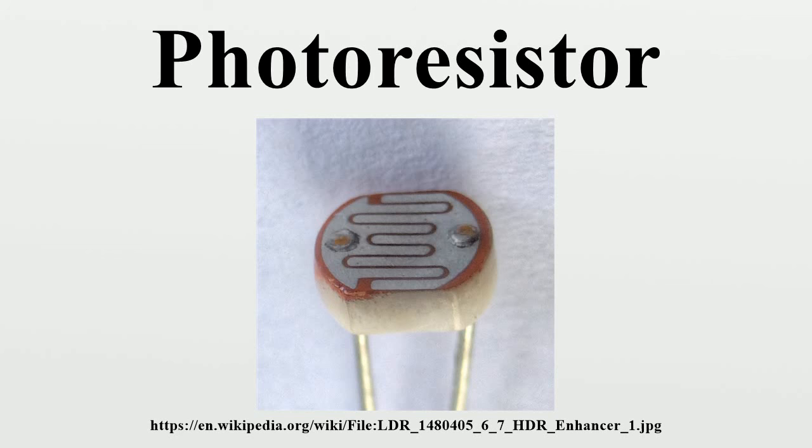Photoresistors also exhibit a certain degree of latency between exposure to light and the subsequent decrease in resistance, usually around 10 milliseconds. The lag time when going from lit to dark environments is even greater, often as long as 1 second. This property makes them unsuitable for sensing rapidly flashing lights, but is sometimes used to smooth the response of audio signal compression. Applications. Photoresistors come in many types.